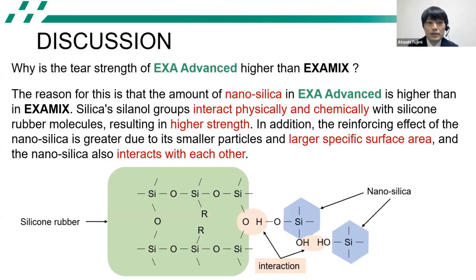Discussion. Why is the tear strength of EXA Advanced higher than Examix? The reason for this is that the amount of nanosilica in EXA Advanced is higher than in Examix. Silica's silanol groups interact physically and chemically with silicone rubber molecules, resulting in higher strength. In addition, the reinforcing effect of the nanosilica is greater due to its smaller particles and larger specific surface area. And the nanosilica also interacts with each other.